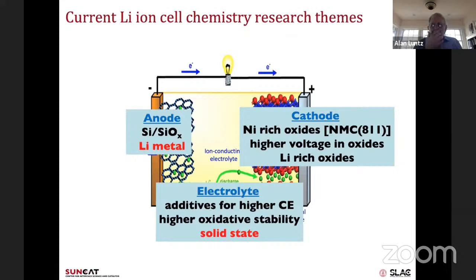Okay, on the electrolyte, for years, people have played a game of trying to optimize the SEI by putting in a little additive of this or a little additive of that. In fact, people tell me they're up to 50 additives in some of the commercial batteries now, just trying to stabilize this SEI so you have a very stable SEI and a high coulombic efficiency, long cycle life.